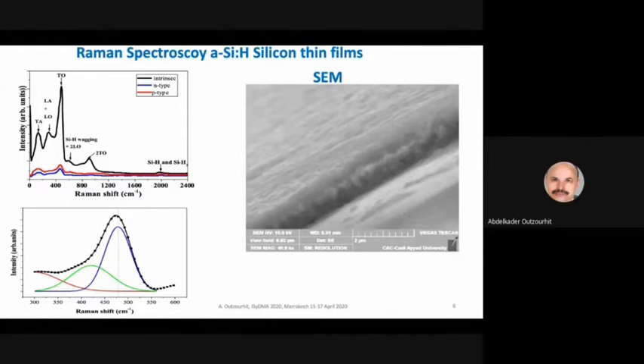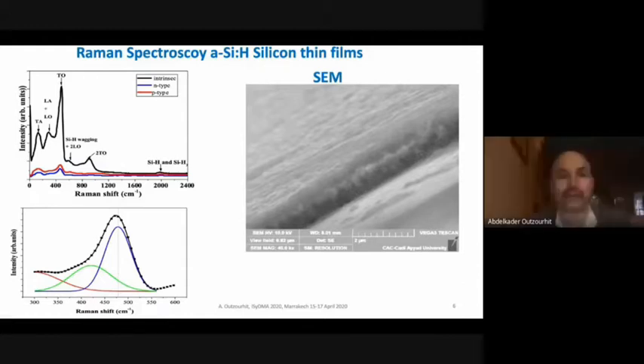No peak that is characteristic of crystalline silicon or microcrystalline silicon or nanocrystalline silicon that usually appears around 520 centimeter minus 1 is observed, which suggests that the films deposited under these conditions that are mentioned above are all amorphous in nature.